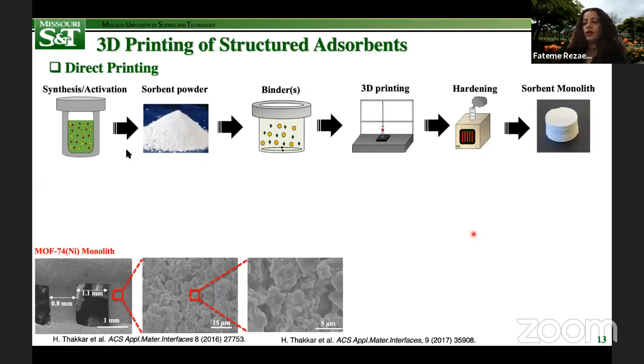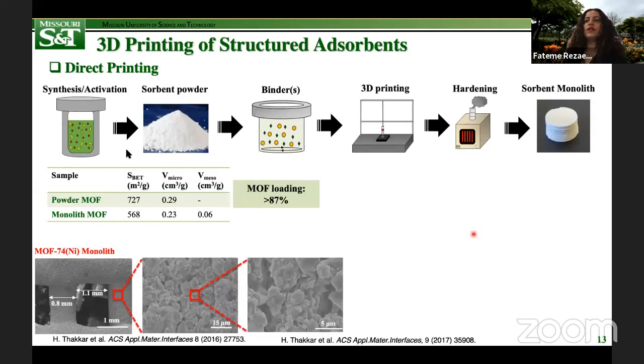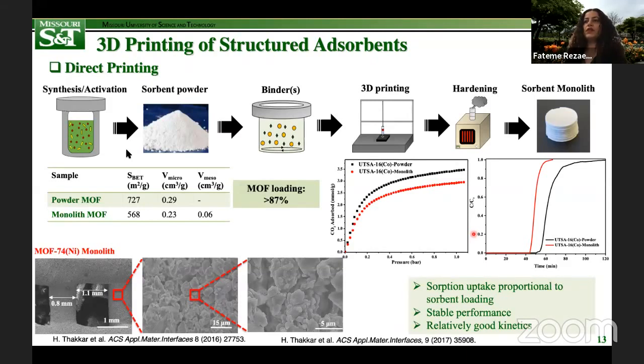This approach could yield relatively high adsorbent loadings, typically greater than 85%, with high porosity comparable to that of parent powder. However, lowering the amount of binder will compromise the mechanical stability of the final pieces. We have successfully employed this method for various sorbents such as zeolites, mixed metal oxides, MOFs, ZIFs, and also aminosilicates. Some of the adsorption performance results of self-standing MOF-74 monoliths are presented here.